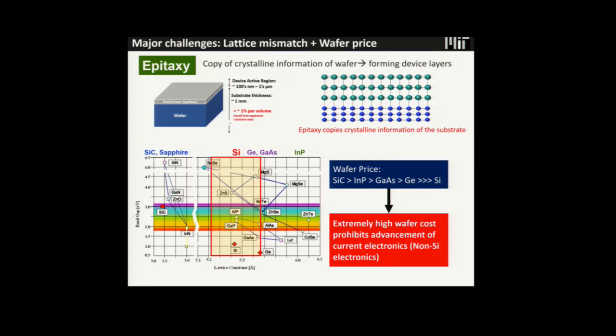The epitaxial process is tricky, especially if you want to use a silicon wafer as a template to grow a device layer. It is extremely challenging because there are so many useful types of semiconductor. But if you use silicon, the epitaxial device layer that you can grow is only in this range, a very narrow range. You have to miss the very important and useful materials all around here.